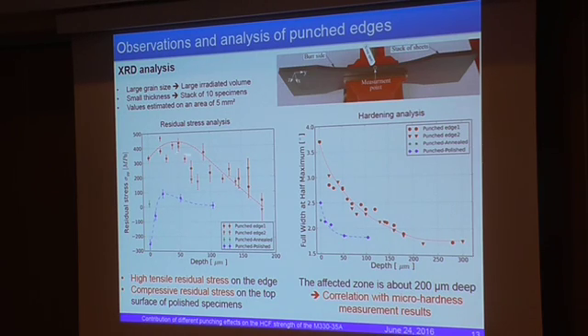So we measure residual stresses on the top surface and then under the surface by removing some layers. And here is what we get for punched edges. So we have pretty high tensile residual stresses in the loading direction, which is also the rolling direction. And these residual stresses are the same order as the initial yield stress. And they decrease up to about 200 microns depth.